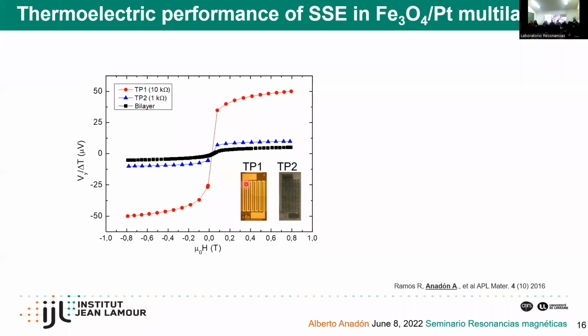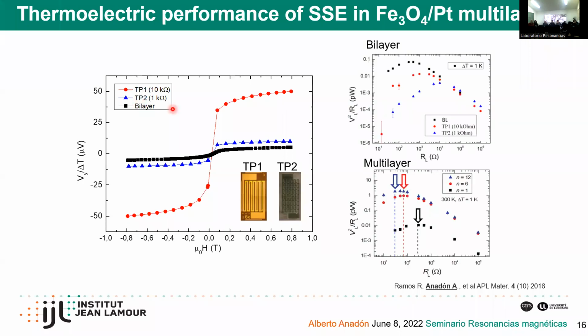But when you connect a load resistance into the system to obtain the power, we were surprised to see that the power that we obtained was highest in the case of the complete bilayer. So we are comparing here both devices with a single bilayer with no lithography in it. So basically, the power that we obtain in the system is related to the area of the spin conversion. The larger the area for spin conversion, the more power we are able to obtain from our system.